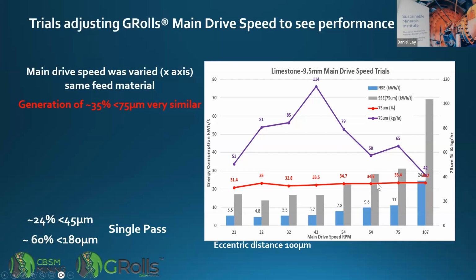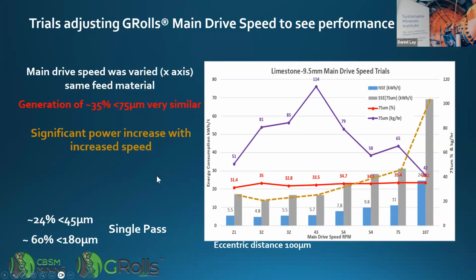So when we dropped them down, we found there's a bit of a sweet spot where we have very high production rates. This is the percentage of the target, 75 micron. So that's increased, our energy consumption has gone down, the grey bar here, so reducing in speed. There's a significant power increase with increased speed.